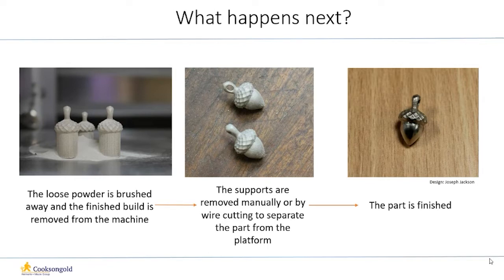Then the supports can be removed with pliers. The parts are then finished the same way you would a piece that has been cast or fabricated. The finish of the part after it is printed is a matte uneven surface. The supports that are removed leave witness marks, which can be emeryed away. The surface facing upwards is called the top skin. It is the smoothest surface and requires the least amount of finishing.